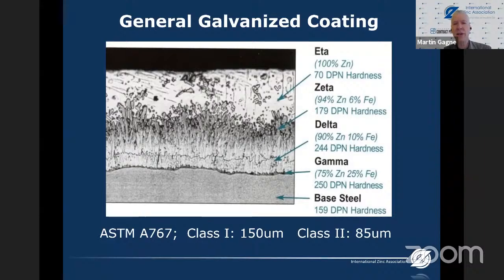These are quite hard. It gives quite good abrasion resistance to the coating. Now, we do know that reinforcing steel is made mostly from recycled steel, and silicon is a very inexpensive strengthening element for steel. Although silicon can destabilize this coating and increase the proportion of intermetallics compared to the free zinc layer at the top. And this can have some consequences for forming the rebar, but it will still provide the